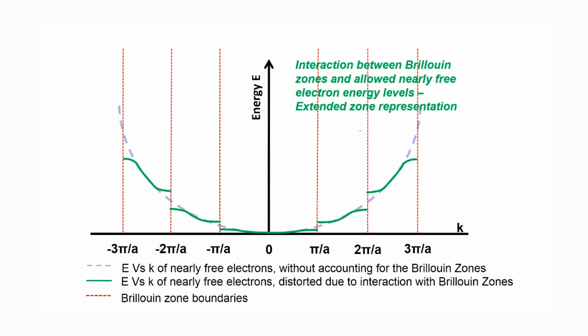Now, at the Brillouin zones, this is exactly what is happening. So, you have these boundaries, these dotted line boundaries which represent this periodic structure that is present in the material. When a corresponding wavelength touches that boundary, diffraction occurs. So, at these boundaries, wherever the free electron parabola is touching these boundaries, the condition for diffraction is valid, okay.